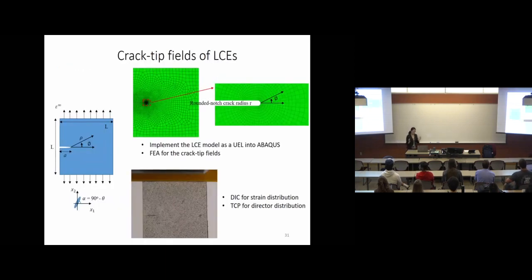Okay, now we have all the tools. We are ready to look at the results of the liquid crystal elastomer and the crack tip. We are considering a liquid crystal elastomer with an edge crack of length a. Now we apply external displacement or external strain to pull the material. We assume the crack doesn't propagate, but we are looking at the field in front of the crack tip. In the finite element, we consider a rounded crack, but we need to make sure the mesh is refined enough to capture the crack tip field. Then we are using DIC and TCP to observe the field in the material.